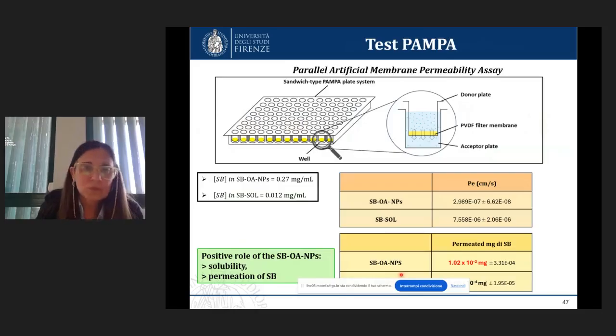With the PAMPA test, we observed that the nanoparticles of oleanolic acid improved not only the solubility of silibinin, but also the permeation, because with nanoparticles we have a very high amount of silibinin permeating with respect to silibinin alone, and a good result about in vitro permeation.